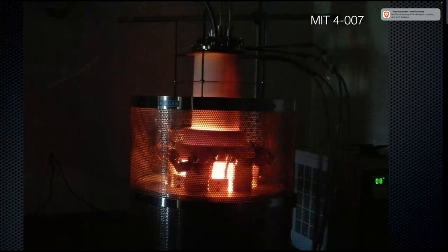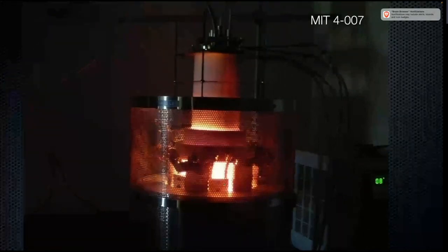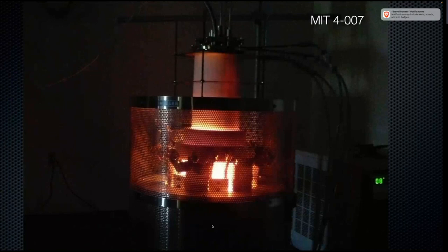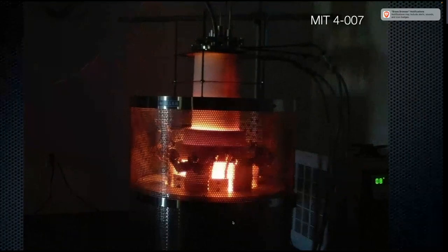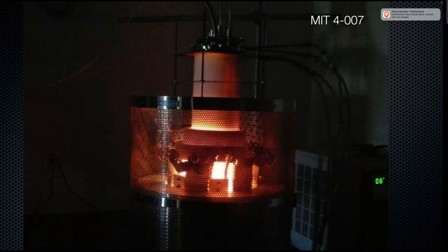So here's some early work at my laboratory at MIT. This is an alumina tube, and it's operating at almost 1600 degrees. You can see it's glowing white here because down below where it's dark, this is where the molybdenum disilicide windings are. So this is where the electrodes are, the cathode and the anode. And you see up here at the top, there's a cap with feed-throughs. So you're going to have feed-through for the cathode, feed-through for the anode, feed-through for a thermocouple. And there's even a port for a camera.